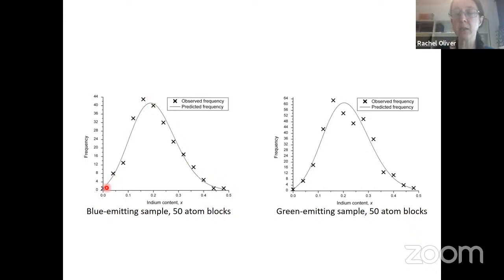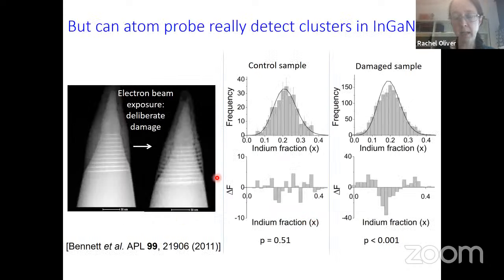So this curve is what we'd expect for the single phase region I was talking about on our phase diagram. And the data follows it really quite nicely for both the blue emitting and the green emitting material. So that suggested that these indium-rich clusters, these big blobs of high indium content, were not actually the key answer to why LEDs work so well. Atom probe wasn't finding the non-random clusters that we were expecting from the transmission electron microscopy data.